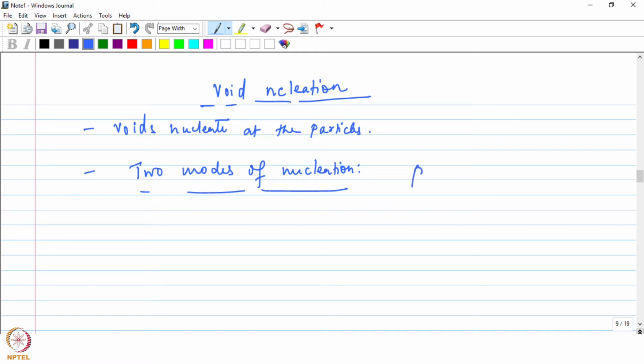One is through particle cracking, and the other is through interface decohesion. So here also you can see the interface bonding is going to play a role. In case of a weak interface, there will be a decohesion between the particles and the matrix, like how we have seen in case of fiber reinforced composite. There could be debonding at the interface because of a weak bonding. So here also, depending on the interface strength, the nucleation mode can change.